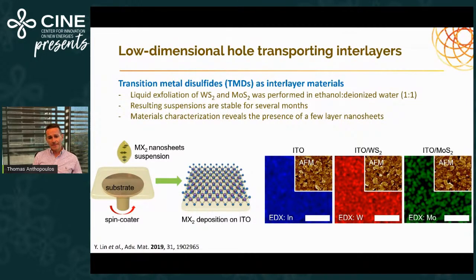But when you do the elemental analysis using EDX of the surface, you can start seeing, of course, the signs of the indium, which is present in the ITO. But tungsten and molybdenum are not present on the bare ITO. And when we have these flakes deposited on top of the ITO, we can now start detecting them. And what you can see here is that the tungsten is a bit more uniform than the molybdenum.